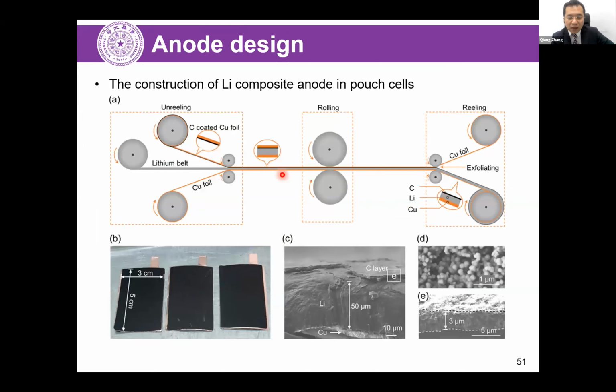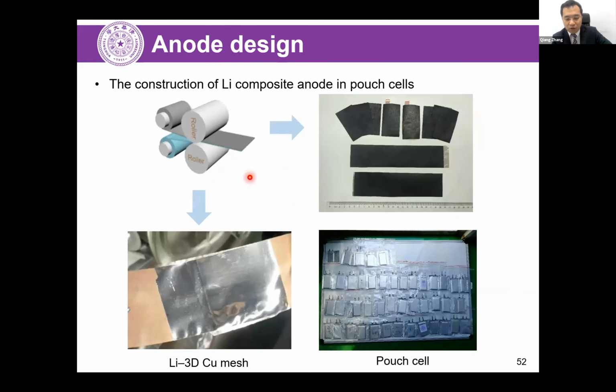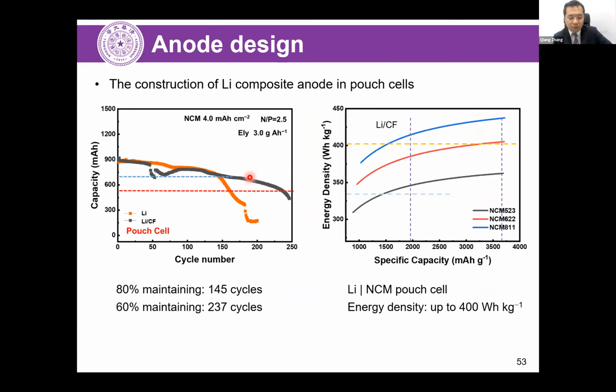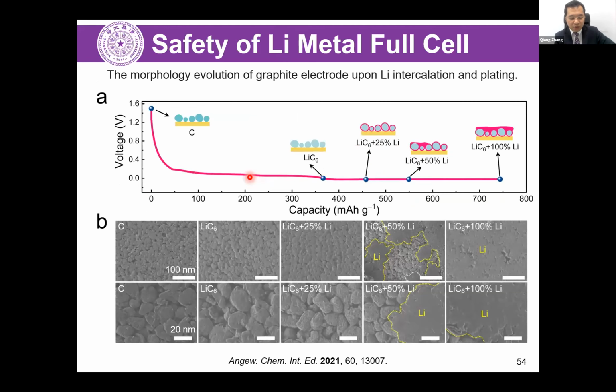And in fact, we try to use the calendering process to build composite lithium metal anodes, and the direct calendering provides large amounts of lithium metal anodes, which makes it feasible to demonstrate the chemistry in a full cell. And it is found that 400 watt-hours per kilogram can be available if we can pair some high voltage potential anode and cathode.